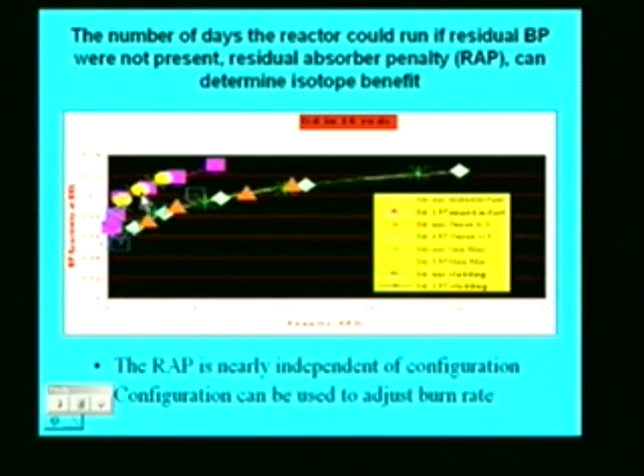Okay, well, something very interesting is that if we plot that for each of the 4 configurations, they all lie on the same curve. So the RAP is essentially independent of the configuration. Well, that was a surprise, at least to me. I still don't understand it. But this is convenient because now the configuration is an independent parameter that we can use to adjust the burn rate.